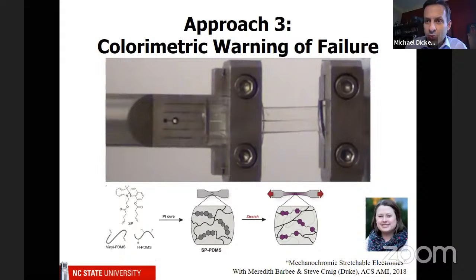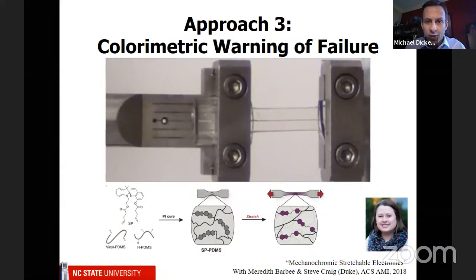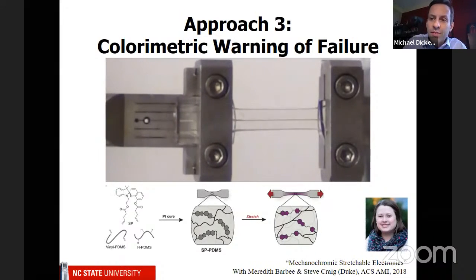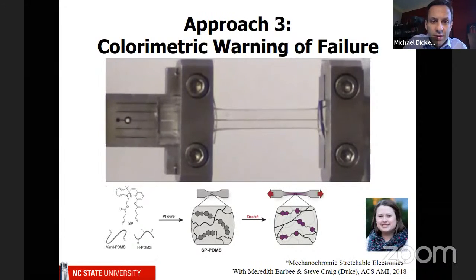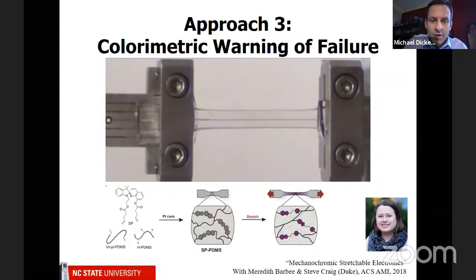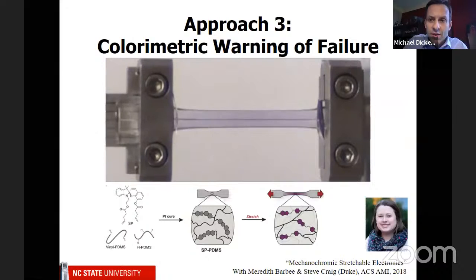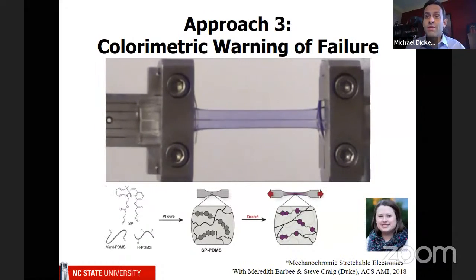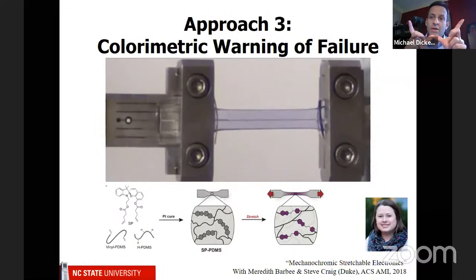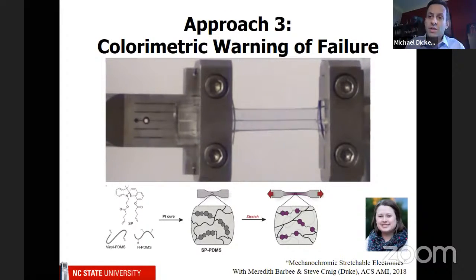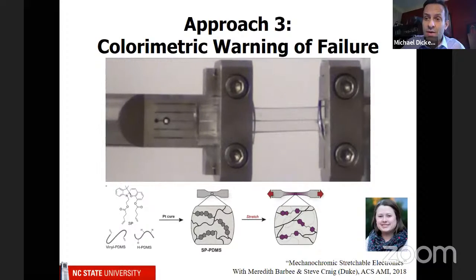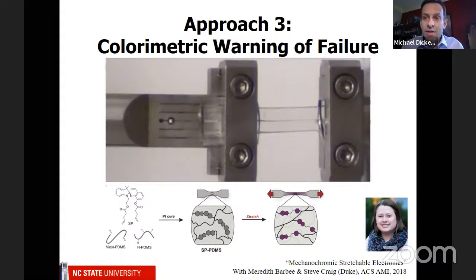So we have a liquid metal wire in here, and we're going to stretch it, and you'll see that right before it's about to break, these molecules in the polymer get stressed and they change color. And so it tells you if this thing is about to break. Those rings open, and when you let it come back, the rings close and it goes back to being transparent. So what this does is it allows you to know before this material is going to break, which is very nice.